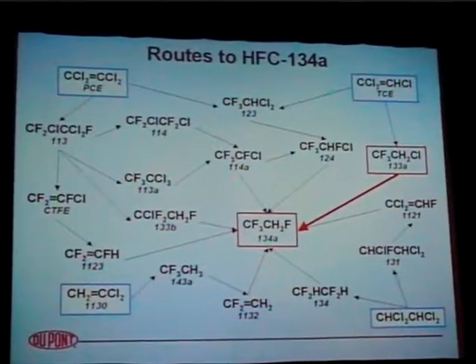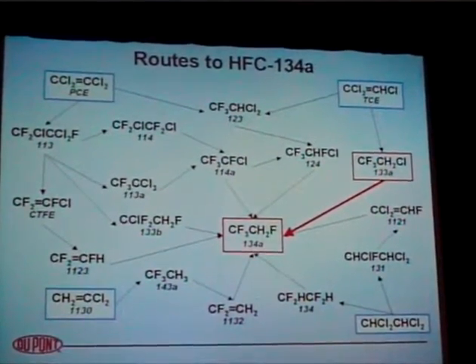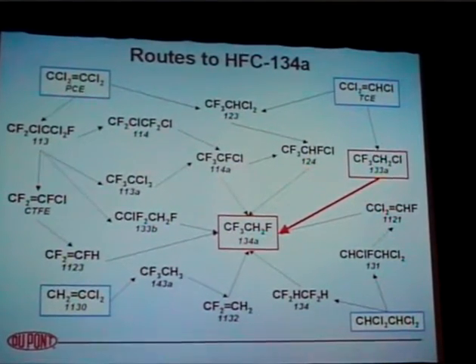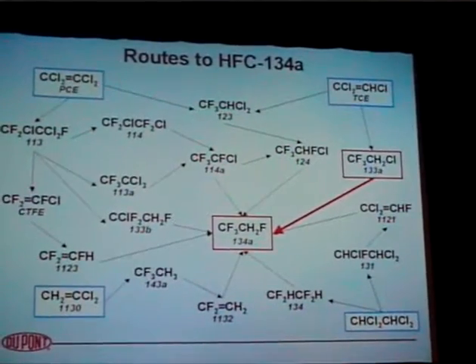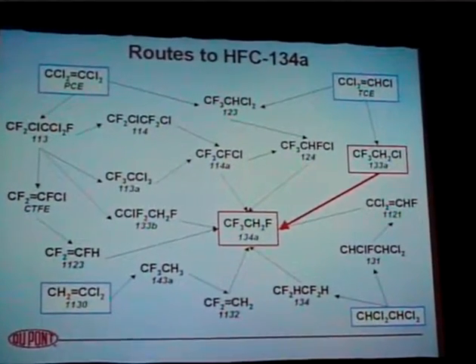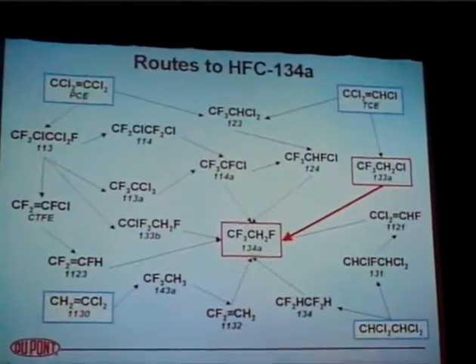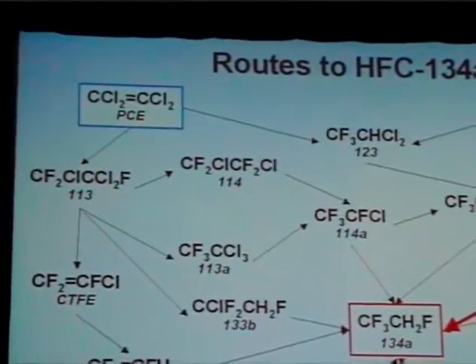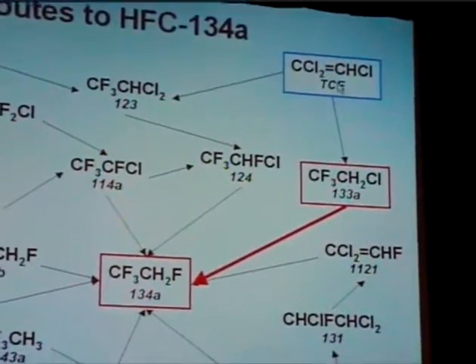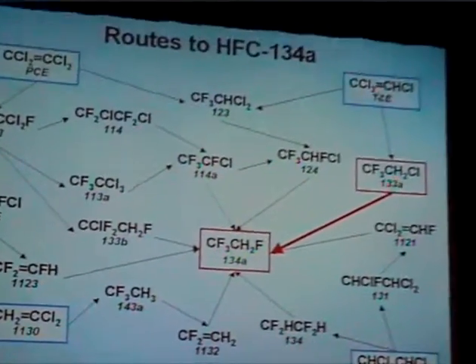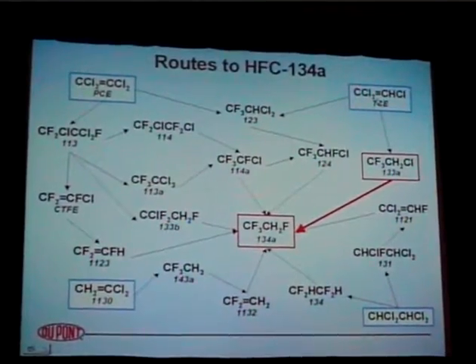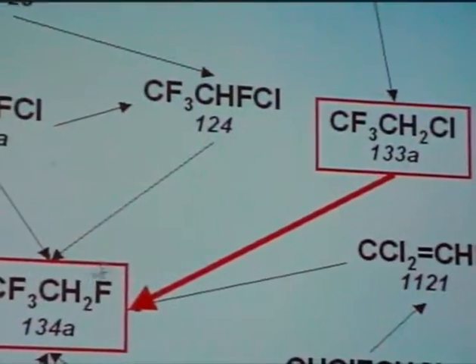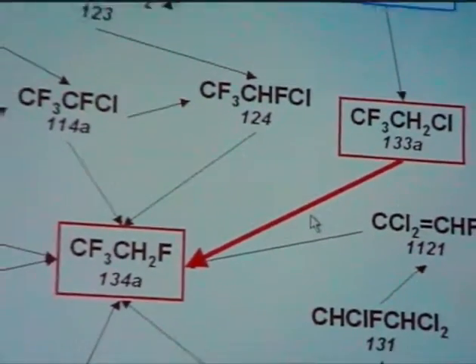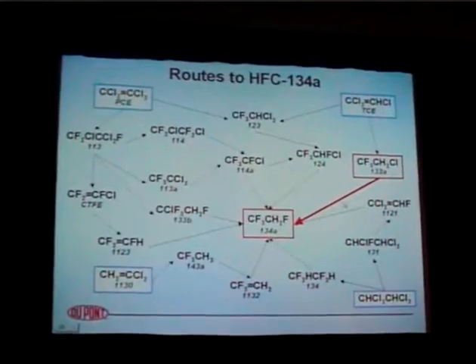Back in 1986, just before we announced the phase out, we all got together at DuPont. We put together this chart for 134a. We said, okay, what's the best way to make 134a, shown in the middle there? And we didn't know at that time, so we had to look at all of these routes and decide which was the most attractive to go after. And there are lots of patents, lots of catalysts that were worked on for these various routes. But I'm going to concentrate on only one reaction. That's the second step of this process, starting from trichloroethylene, going through that molecule 133a, chlorotrifluoroethane, and then on to 134a. So I'm going to talk about this reaction shown in red here, since that's been the route that has been commercialized by most of the companies in the world.